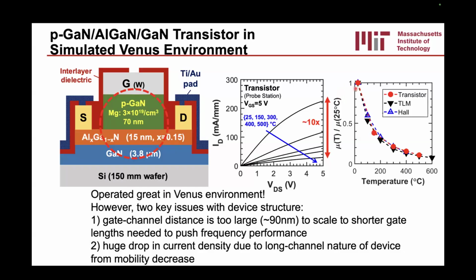And this is just to put the nail in the coffin. If we look at the field effect mobility extracted from the transistor compared to Hall measurements or TLM measurements, assuming a constant 2DEG density, we can see that they overlap very well, indicating that the transistor field effect mobility degradation is from the same phonon scattering mechanisms we see in Hall structures.